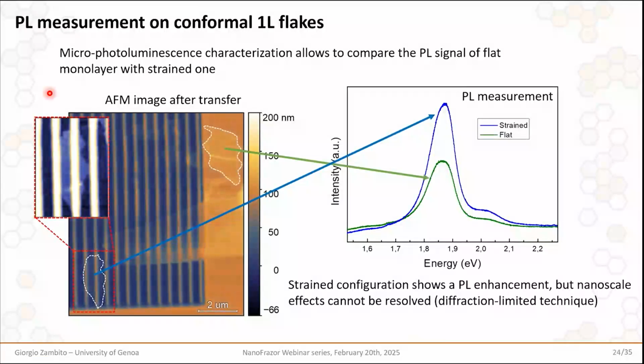So to start understanding whether there was some kind of strain-induced effect on the optoelectronic response of these materials, we tried to observe the photoluminescence coming from monolayer flakes lying on flat and patterned PPA respectively. And we observed that there is actually an enhancement of the photoluminescence coming from the strained flake with respect to the flat ones, with an enhancement factor between 2 and 3.